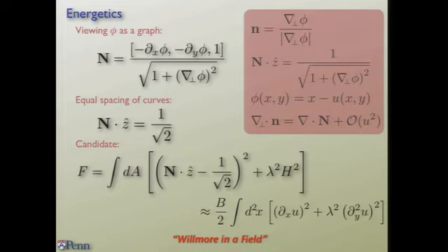If I didn't have the compression term at all, this is called the Willmore problem. And you fix the topology of the surface, which essentially means fixing the sets of dislocations in the surface. And you can then minimize h squared subject to this constraint. And then there's this extra piece, which is like a field that's telling me the normal wants to point in a particular direction. So it's rotationally invariant in the xy plane.